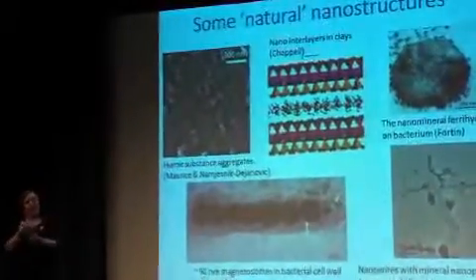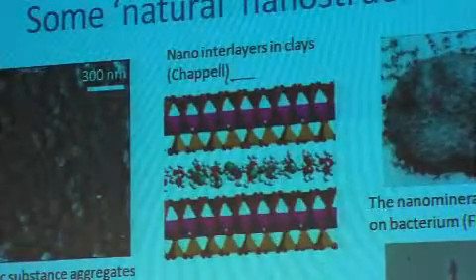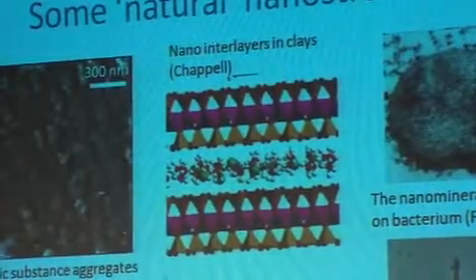But at any rate, swelling clays have interlayers that are just at the border between angstrom and nanometer scale. And as they swell, they can take molecules into them, and the conformations and reactivities of those molecules can change in the interlayer. So, for example, you may have an organic molecule that has a very complex three-dimensional structure out in water, but if it gets into that interlayer, it may take on a more planar conformation that really changes its reactivity. So this is a nanoscale, angstrom to nanoscale space where you've got different properties than bigger or smaller. We have something we call nano minerals.